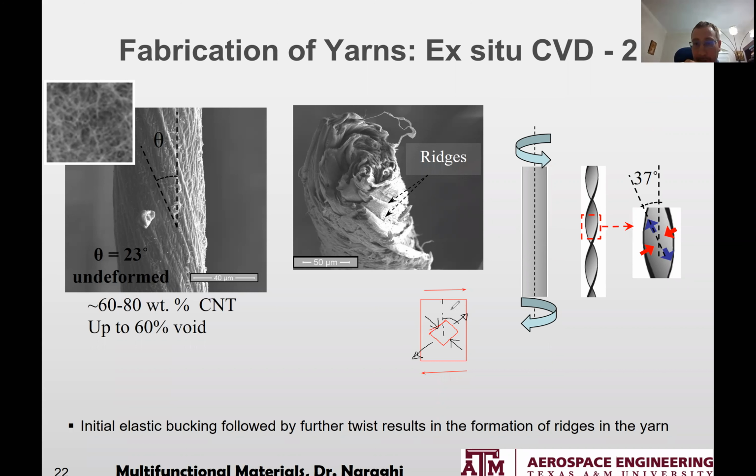These are at a 45-degree angle. Any of you who don't have a mechanics background and would like to know more about this, please let me know during office hours. I can explain that to you. Now, I'm sorry, but one last thing, this angle is not necessarily 45 degrees. In case of pure shear, it's going to be 45 degrees. But when we're dealing with a mat, it's slightly off. It's about 37 degrees because of some in-plane deformations.